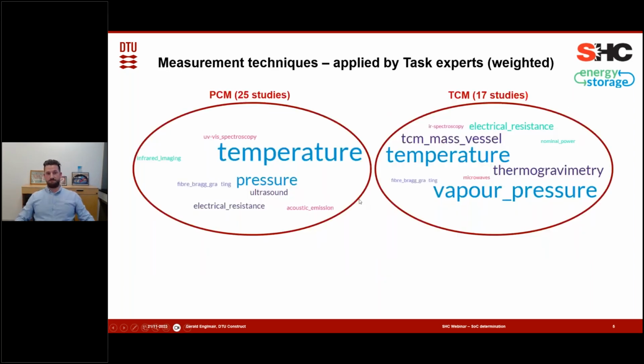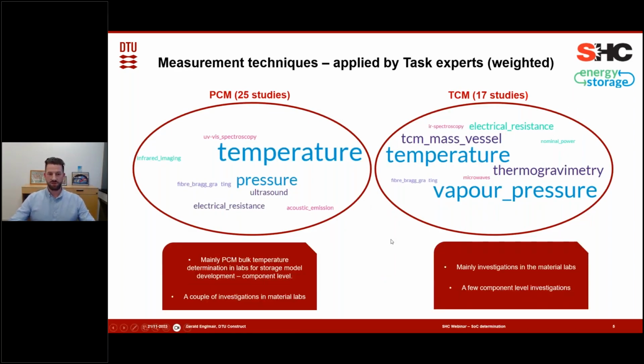And then we had a different picture. We basically saw a focus for phase change materials on measuring the bulk temperature, which is the standard for labs in order to make models, for example, and a couple of investigations also in material labs on a smaller scale with the newer methodologies. It was vice versa for thermochemical materials, where you had a huge variety of investigations from the material labs, but only a few which are scaled up. So we can say that's a pilot storage where you try to investigate something.